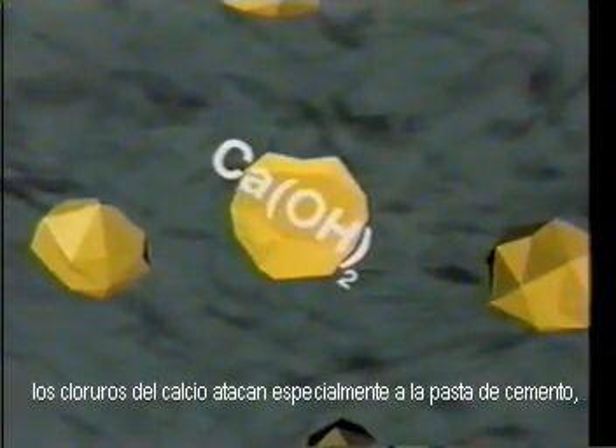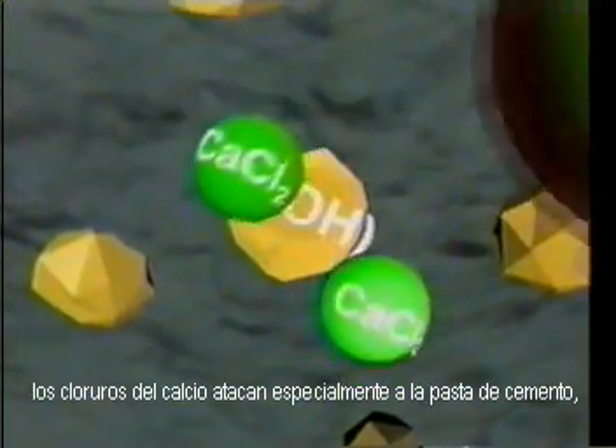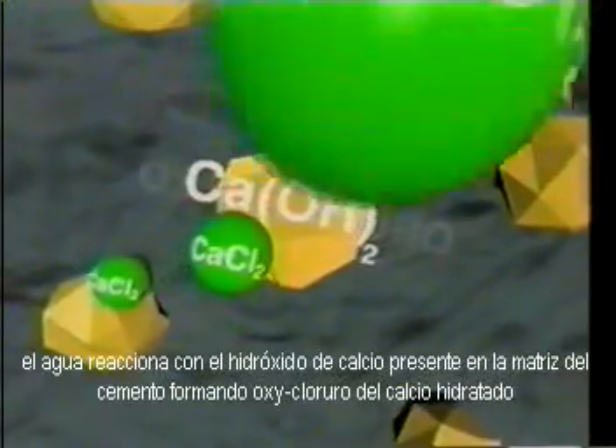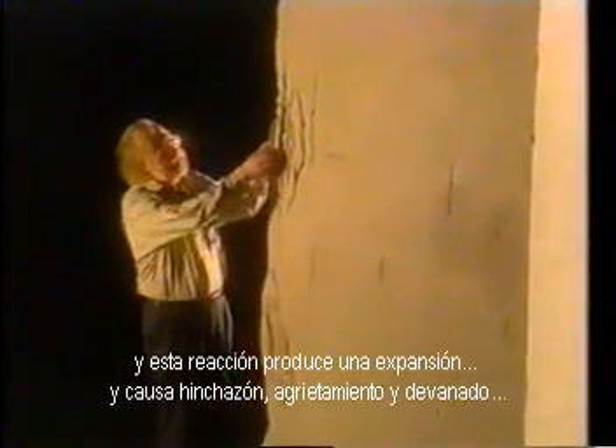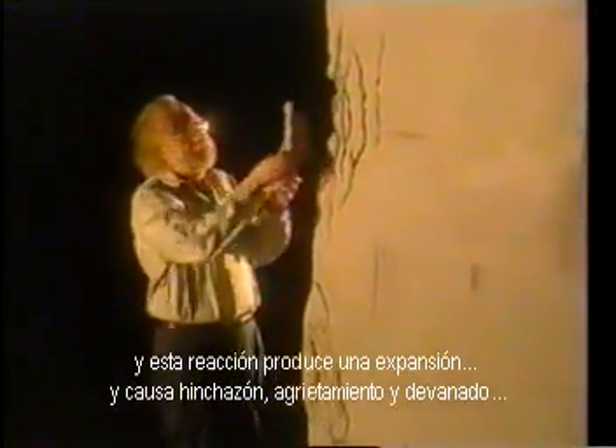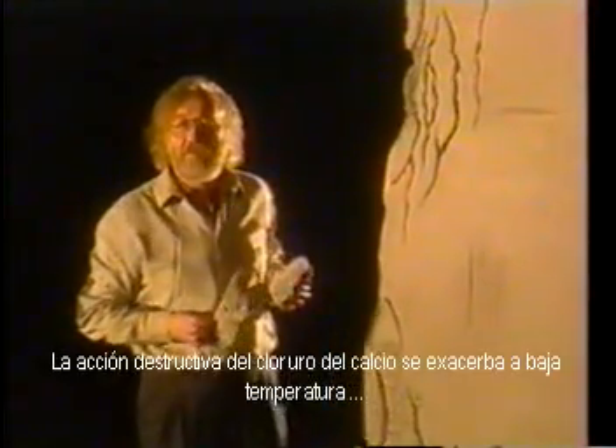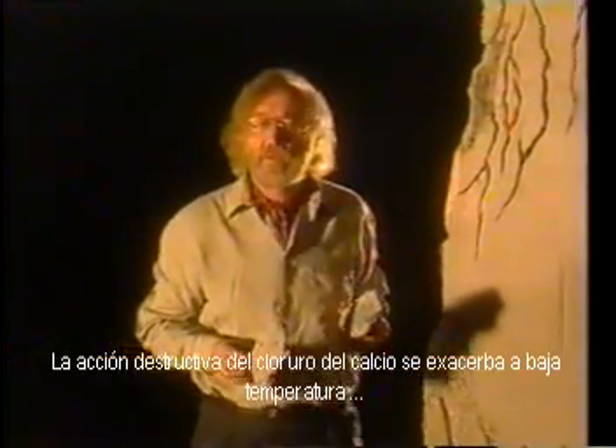Calcium chloride especially attacks the cement paste. What it does is react with the calcium hydroxide present in the cement matrix, forming calcium oxychloride hydrate. And this reaction produces an expansion. It causes swelling, cracking and spalling. The destructive action of calcium chloride is exacerbated at low temperatures.